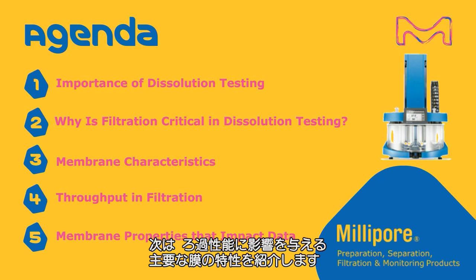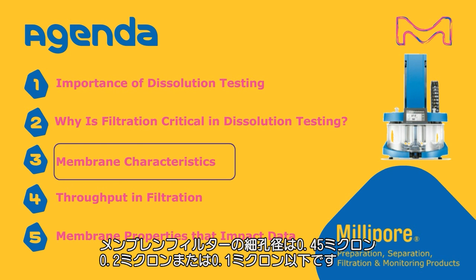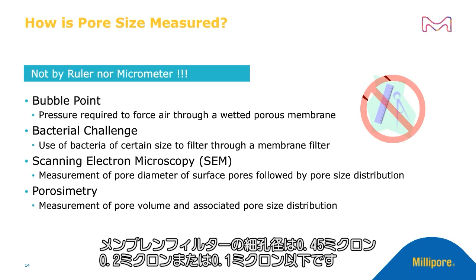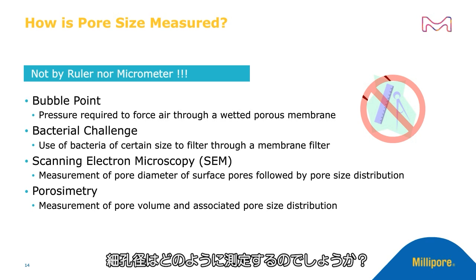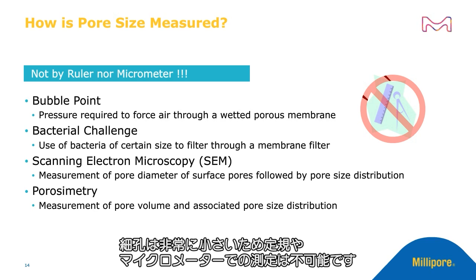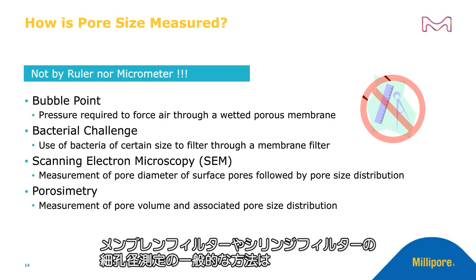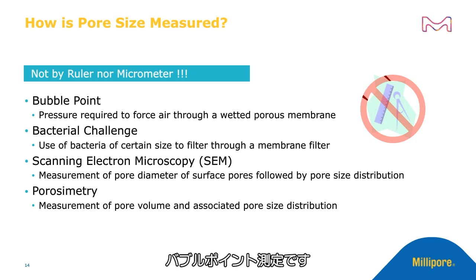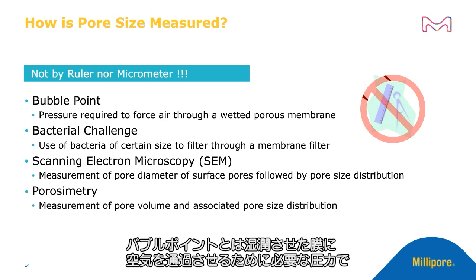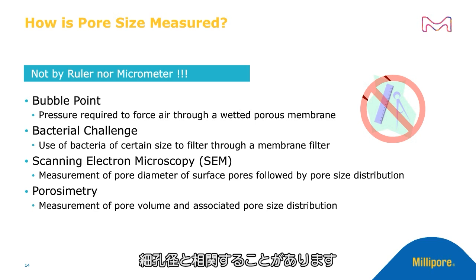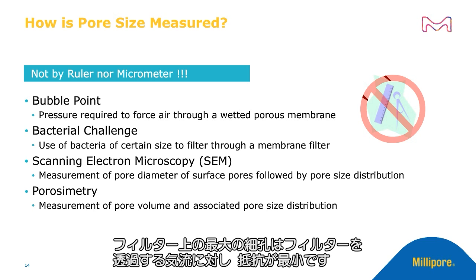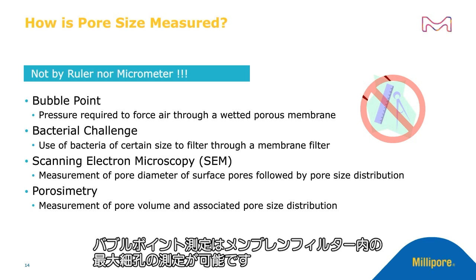So now let's talk about some of the key membrane characteristics which impact the filtration performance. Previously, I talked about the pore size of membrane filters being 0.45 micron or 0.2 micron or 0.1 micron. So how do we measure these pore sizes? We can definitely not measure them by a ruler or a micrometer because these pores are too small. One of the most commonly used methods for measuring pore size of a membrane filter or a syringe filter is a test known as bubble point. Bubble point is the pressure that is needed to allow flow of air through a wetted membrane. This pressure can be correlated to pore size. Since the largest pores on a filter will have the least resistance for airflow through the filter, bubble point typically gives an answer about the largest pore in a membrane filter.